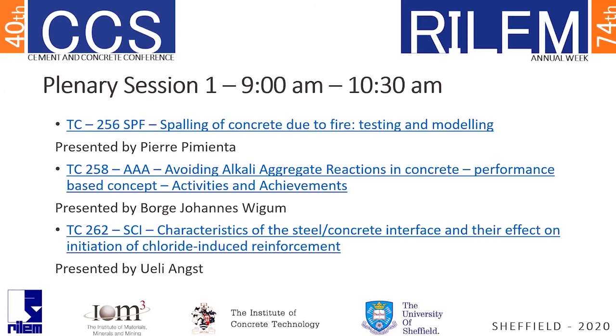Regarding expansion limits, in each country with different reactive aggregates you have to get your local experience of what the critical limit is, and that should be compared with what you see in real structures. Also, you should continue with concrete prism testing, because the accelerated mortar bar test is just a screening test. Another anonymous question asked for a method to assess the alkali reactivity of cement or binder. The answer is the same: if you want to assess the performance of your concrete mix, you need to go for a real performance test — the AAR-10 method, which will hopefully be published in the coming months.